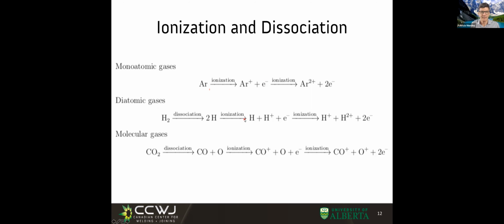In diatomic gases, we have something very similar, but there is a small difference. The small difference is that in these diatomic gases, often they break the molecule before they ionize. So they go from a gas like hydrogen, or it could be oxygen or nitrogen. First, it's going to dissociate into two atomic hydrogen atoms, which are not necessarily ionized. And then as the energy keeps coming, it might ionize, right?